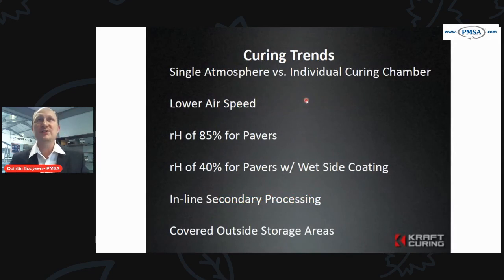Looking towards the future, some trends that are coming around: a single atmosphere versus individual curing chambers. We promote a single atmosphere quite often, where you have a single environment, and in that environment we're able to capture the heat of hydration more readily. And we spread that heat of hydration around through convection, through circulation fans, and if need be, we can add external heat as well, and even moisture into that curing environment.